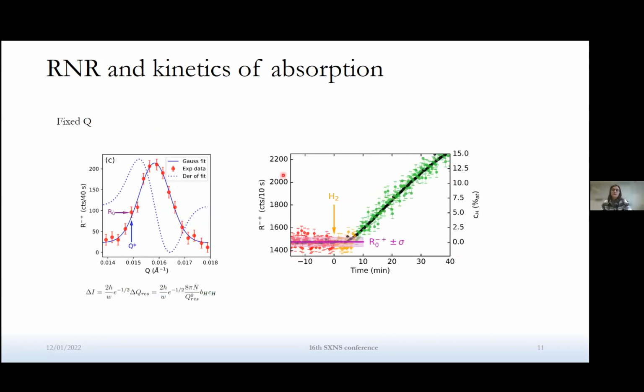And the second mode was that of staying at a fixed Q in the resonance peak and just waiting there. And while the peak is shifting, we detected a change in intensity at this fixed position. And then hydrogen content can as well be retrieved. And here, simultaneously with RNR, we have also performed the in situ resistivity measurement, which is a well-known studied method for kinetics. And you can see in black is the resistivity. It fits pretty well with the neutron data, and shows the same kind of kinetics.